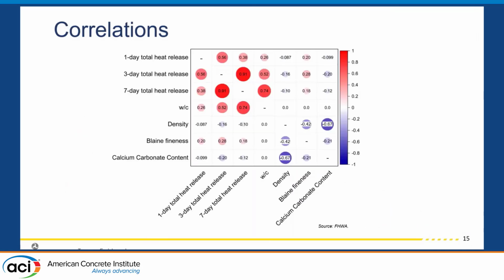So how do those things correlate? Our 3-day and 7-day total heat release correlated really well, which of course makes a lot of sense. Most of your reaction is happening in the first 3 days, and it's only going to go up from there. So your 7 and 3 days should be that similar. Then your 7-day total heat release is very related to your water-cement ratio. Once again, this makes a lot of sense.